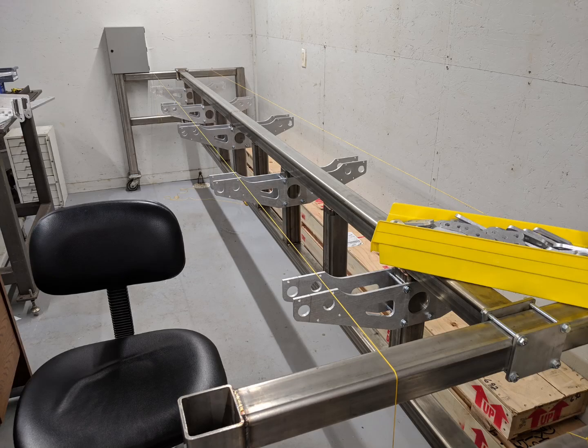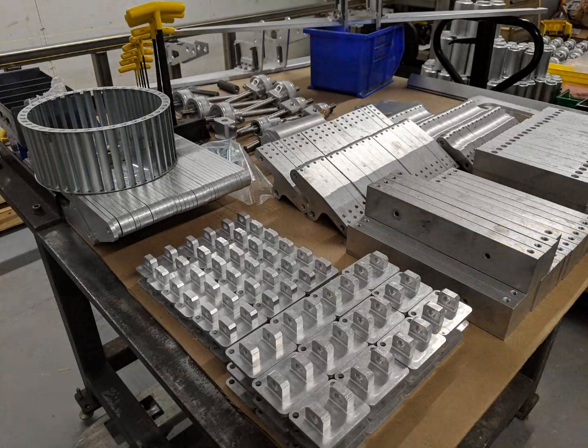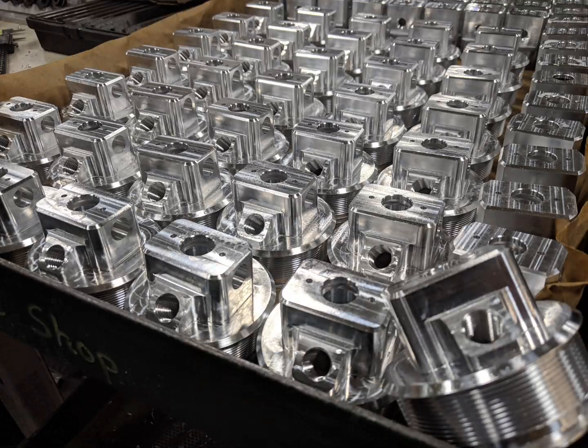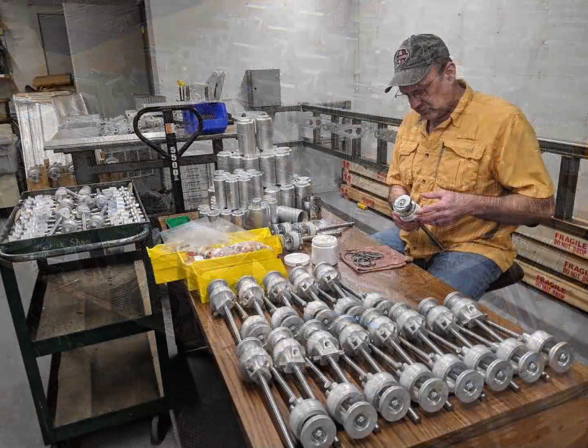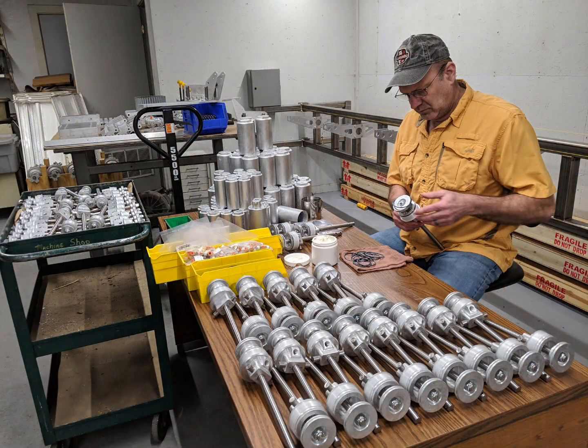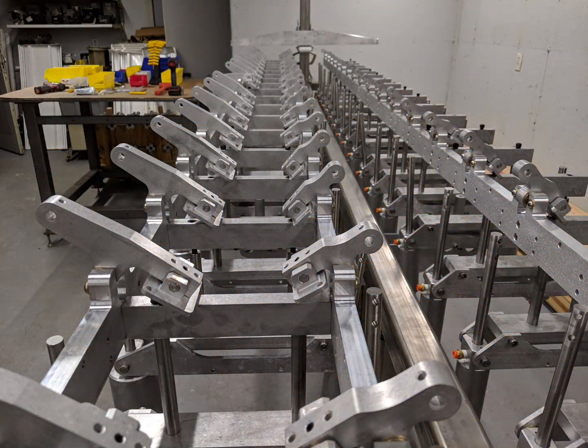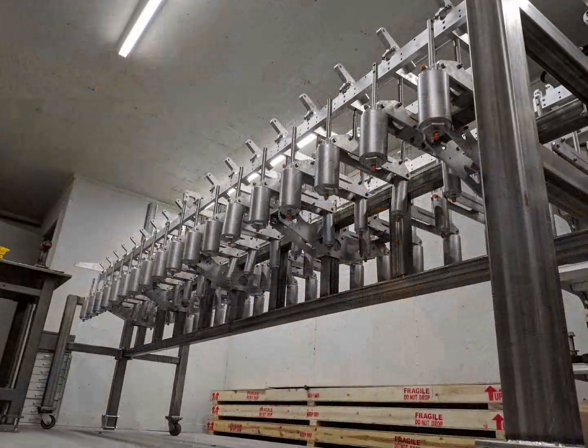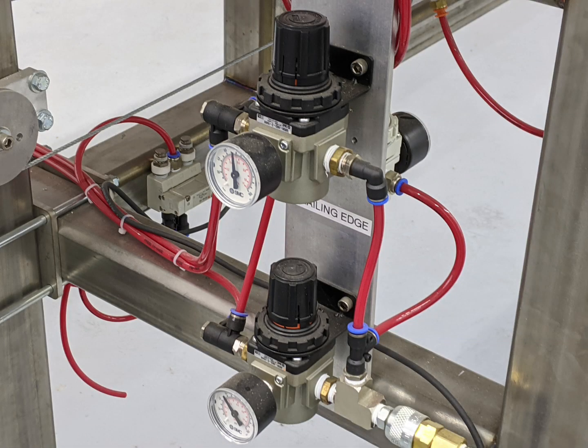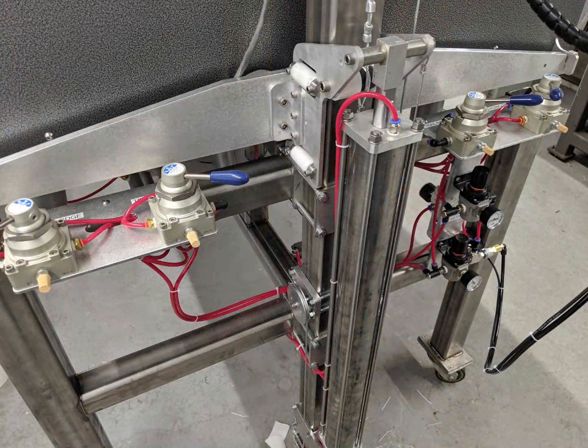It's built upon a rigid stainless steel frame. We designed and made all the internal components in-house, including all the air cylinders that apply the clamping pressure for the adhesive. There are 32 individual air cylinders under this oven. Since the leading edge has a wider adhesive strip and more surface area than the trailing edge, a greater clamp force is required. The cylinders are sized accordingly, and their air pressure is controlled precisely.